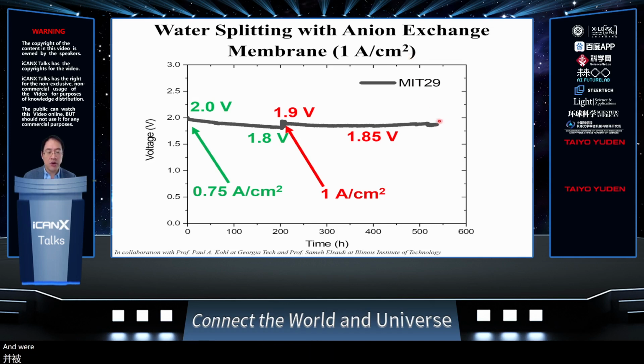And we're able to run for 550 hours at the membrane electrode assembly level with 1.85 volt. So the thermodynamic voltage is 1.23 volt. So this is really very good performance and very durable full cell system.